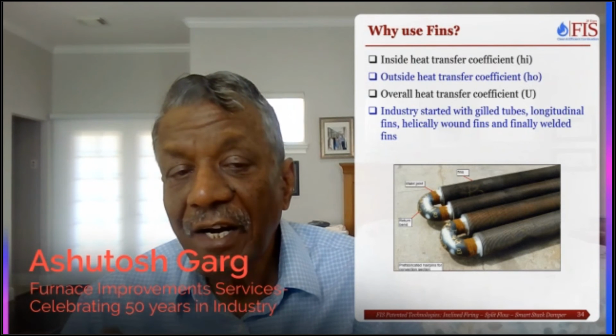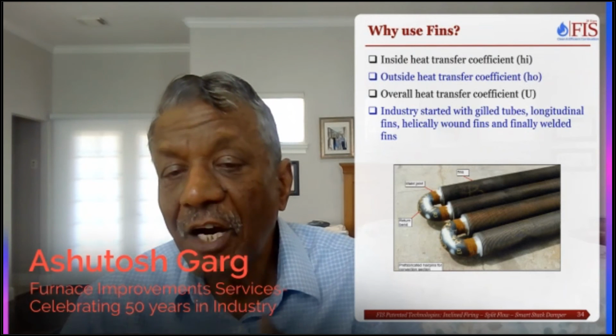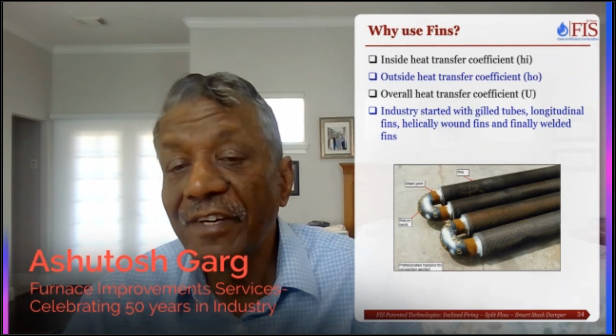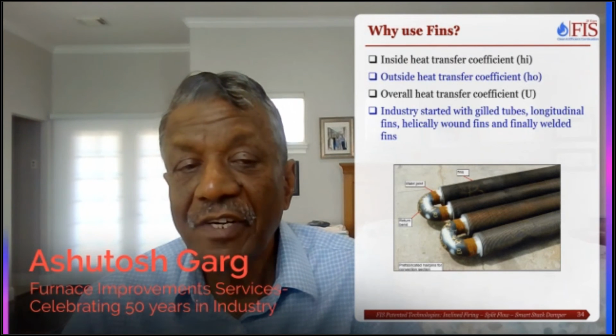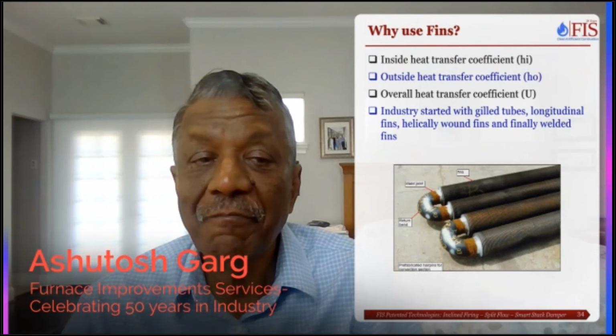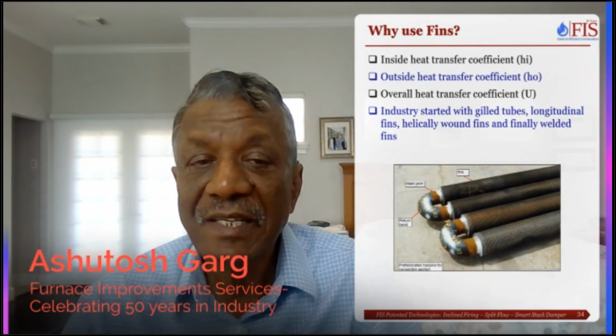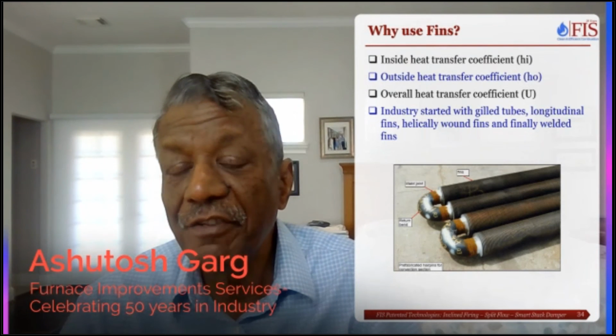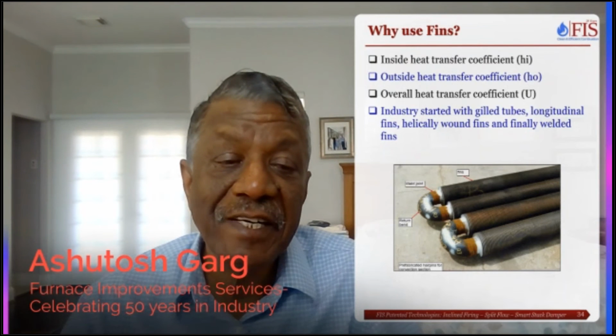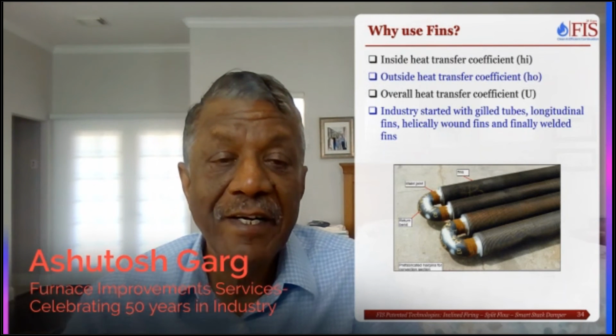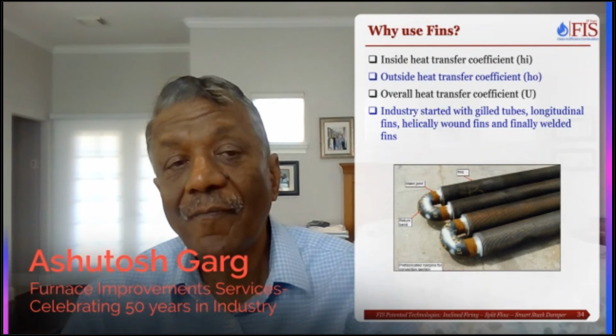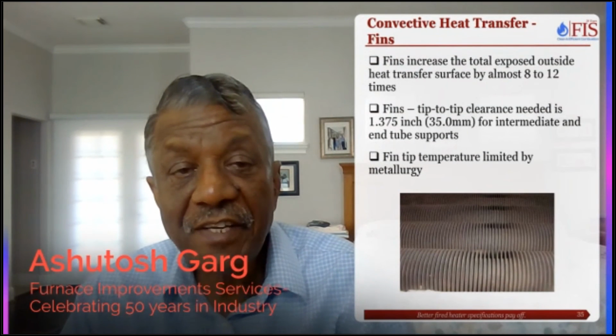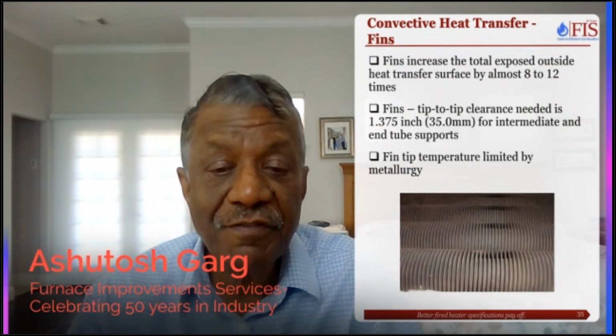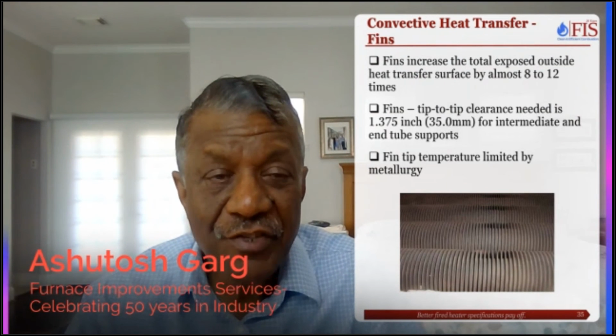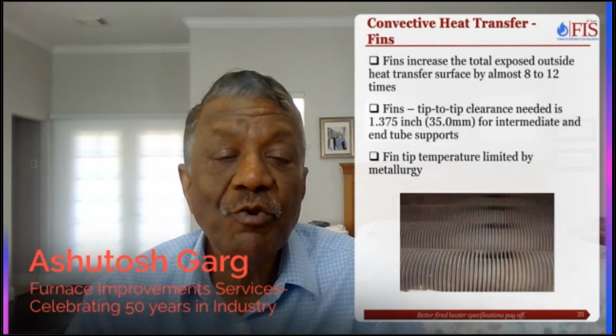So it's the outside heat transfer coefficient which is controlling. And that is why by increasing the outside heat transfer surface, we are able to recover more heat. That's why we use fin tubes, because there is so much of difference between the inside heat transfer coefficient and outside heat transfer coefficient. So once we put fins, we can increase the surface of heat transfer by almost 8 to 12 times.